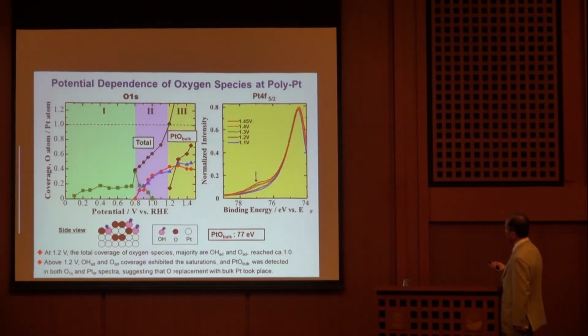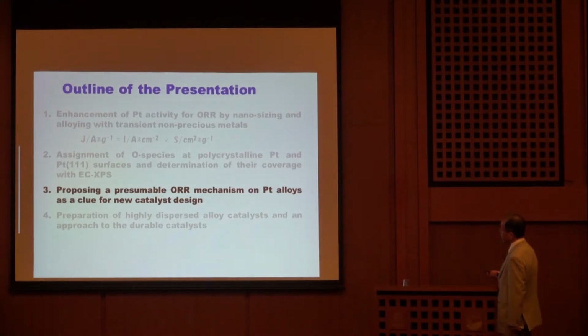Actually, we detected the oxidation signal of platinum on the platinum 4f energy levels like this. That is shown. This is the surface OH or O species, and this is the oxygen species at such a potential region. And now we propose the presumable oxygen reduction mechanism on the platinum alloy as a clue for new catalysts.